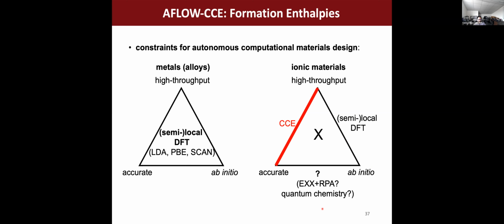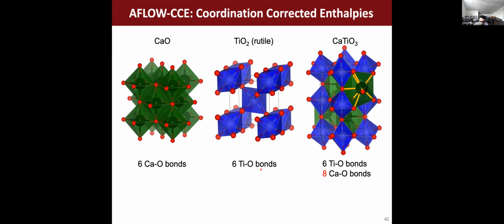If we want it to be accurate and ab initio, there are some approaches, which include exact exchange and RPA. So there are ways of doing it, but it's not going to be high throughput. These are very expensive calculations. So if we want to complete this leg of being high throughput and accurate, we need to use the CCE method, the corrected enthalpies approach. We're going to correct these enthalpies by the coordination. Why is this important? Because there are some corrections that exist in the literature which are purely dependent on just the composition.